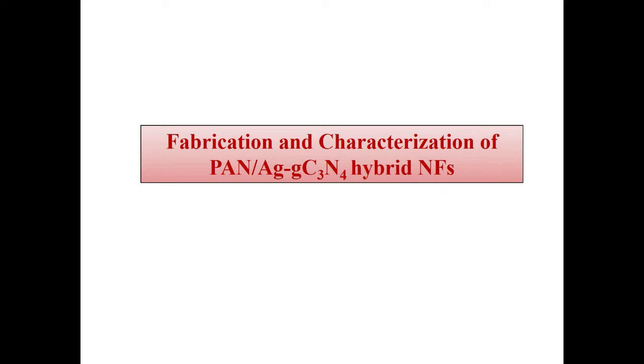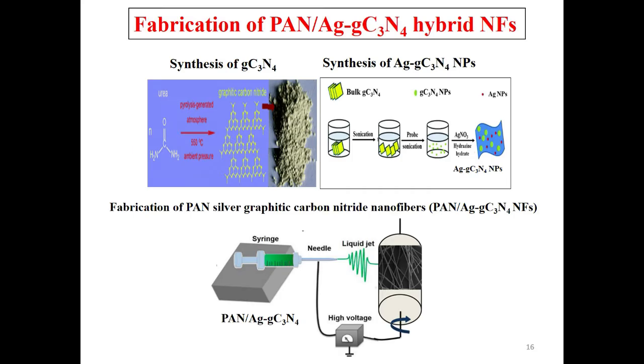Now we go with the first method, that is the fabrication and characterization of PAN Ag/g-C3N4 hybrid nanofiber, that is polyacrylonitrile silver graphitic carbon nitride hybrid nanofibers. Here is the method of drawing of PAN Ag/g-C3N4 hybrid nanocomposite. Initially we synthesized graphitic carbon nitride using urea. We did the pyrolysis under ambient pressure at a temperature of 550 degrees centigrade. There is a formation of graphitic carbon nitride. The powder is gray in color.